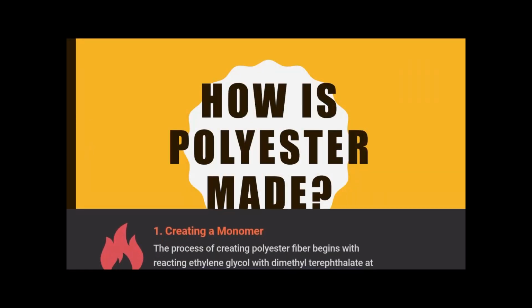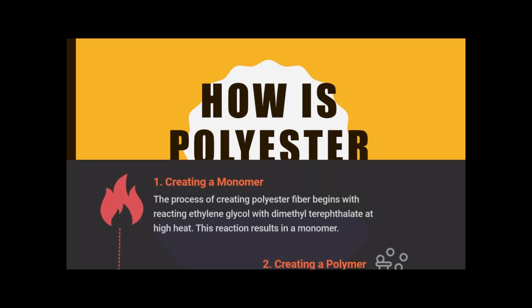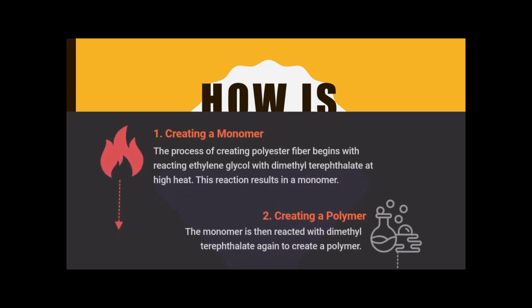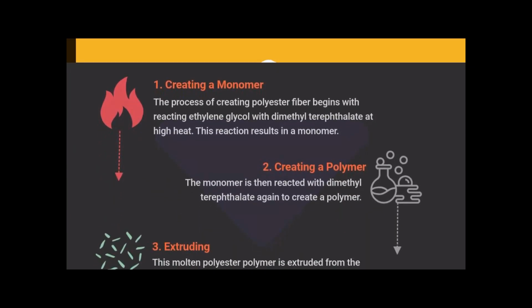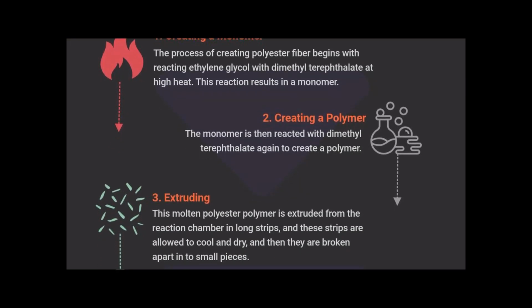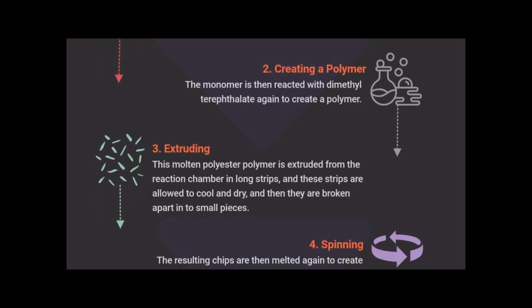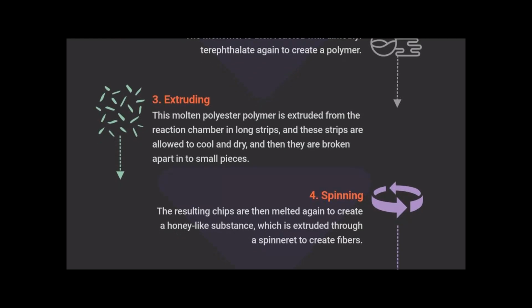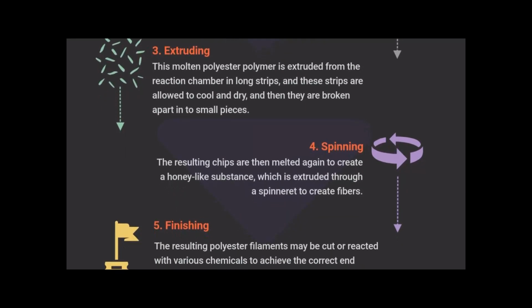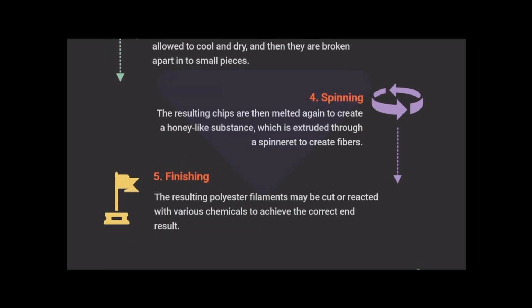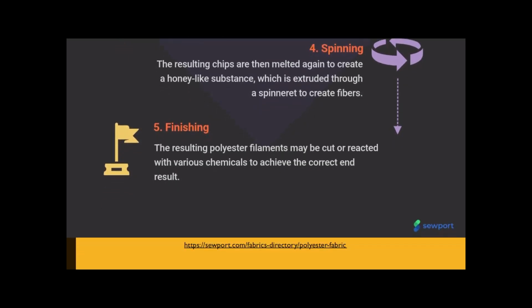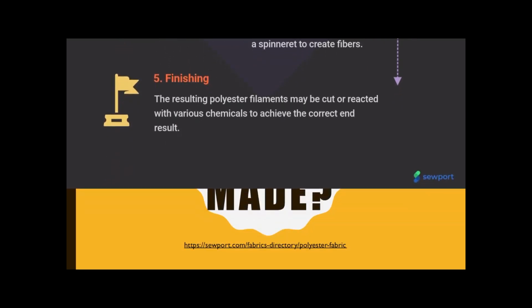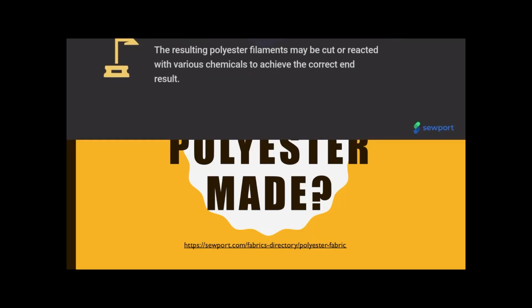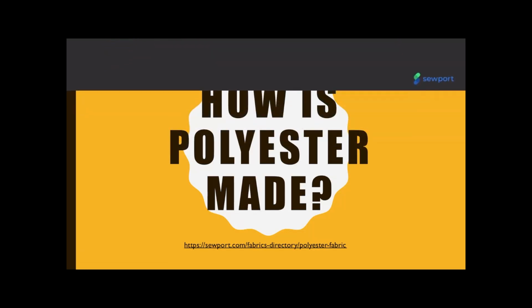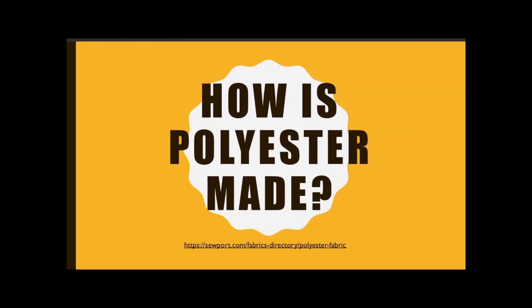Firstly, a monomer is created as the ethylene glycol is reacted with dimethyl terephthalate at a high heat. This monomer is then reacted with dimethyl terephthalate again to create a polymer. Then it's extruded in a chamber into long strips, which are cooled and allowed to dry and then broken apart into pieces. The chips are remelted and then extruded again through a spinneret to create fibers. Then the threads that are created are finished and turned into whatever sort of fabric the polyester is needed for.